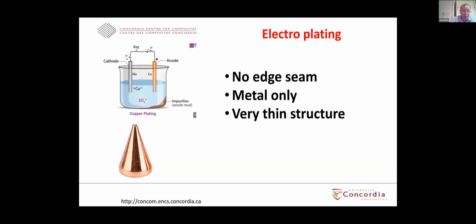So the people at NASA used a method called electroplating, in the sense that they also used a mold, and then put that inside an electrolytic chamber, and they plated copper on top of the mold. From there, they obtained a conical shape that is very thin. That way, they managed to get something that has no edge, and they managed to do the experiment on the cone. They got a result, but still it did not agree with the calculated value. The experimental value was about 60% of the theoretical value.